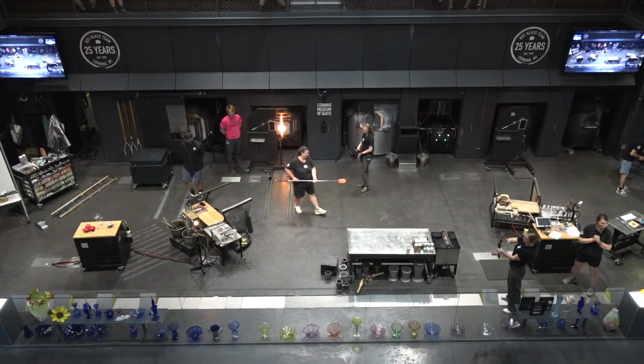Every piece of glass ever made has to be slowly cooled in a process known as annealing. That annealing oven is at a high temperature, around 950 degrees Fahrenheit. We'll take everything that we make and we'll put it into that oven. And then at the end of the day, we'll slowly cool on a computerized slow cooling process. And it depends on the thickness of the material as to how long it cools down for. So for the pieces that we make today, this piece might be a little thicker. This piece is going to have extra things on it. We might cool it for a little bit longer, but generally 12 to 24 hours.